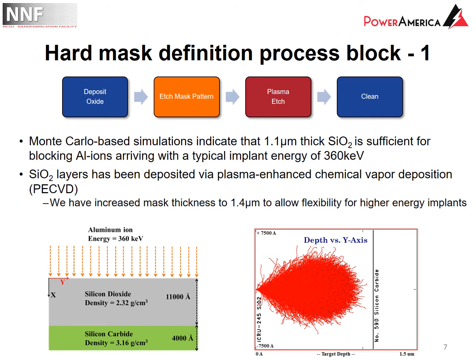So the first thing we had to do is some simulations to determine what thickness of oxide we would need. And the simulations showed us that 1.1 micron of thick SiO2 was sufficient for blocking the aluminum ions arriving at a typical implant energy of 360 keV that is used in silicon carbide processing. So these SiO2 layers have been deposited via plasma-enhanced chemical vapor deposition, and we've actually increased the mask thickness to 1.4 micron to allow flexibility for higher energy implants.